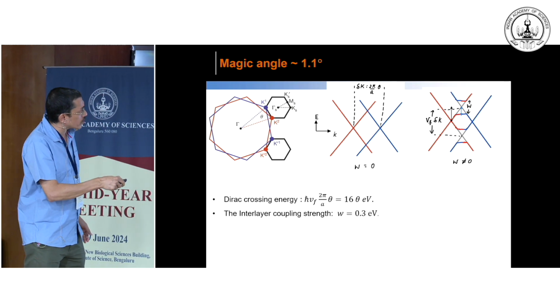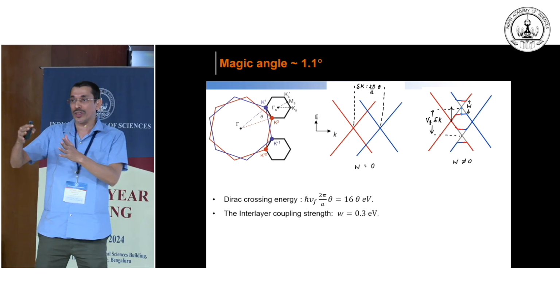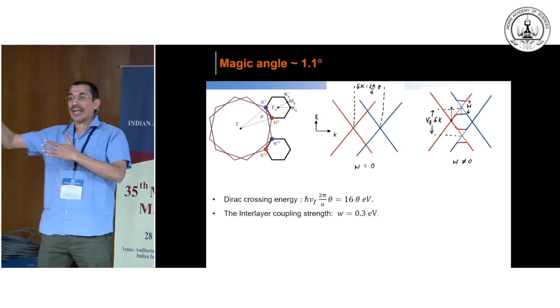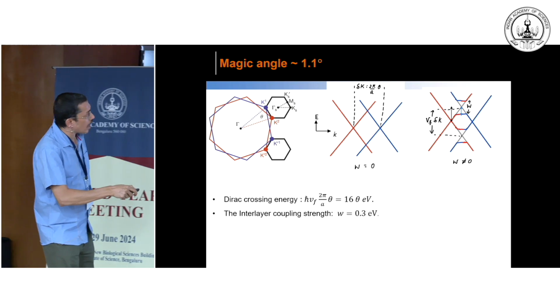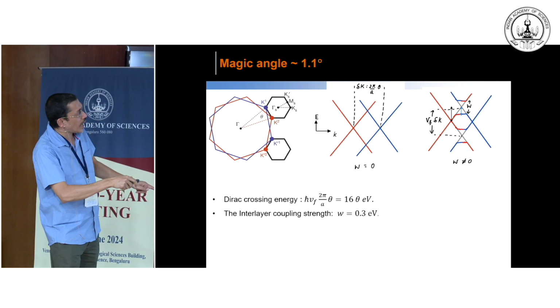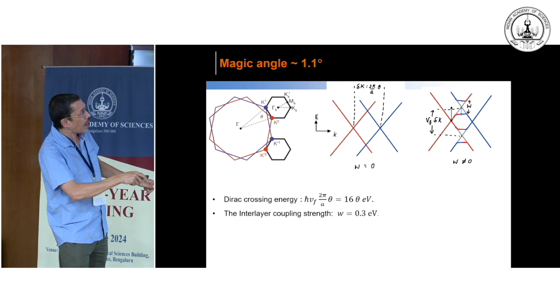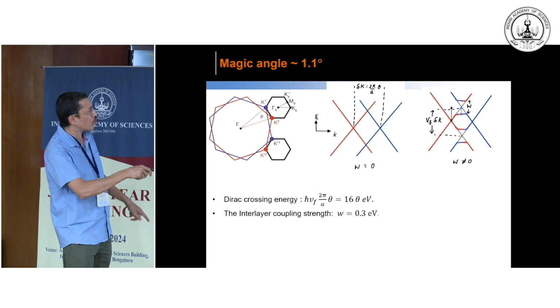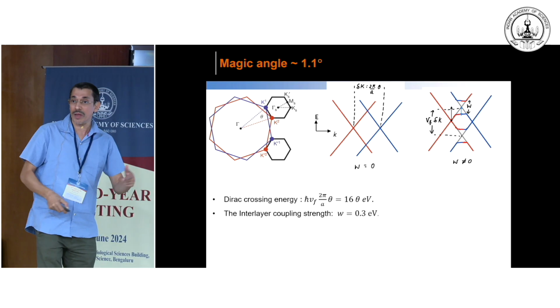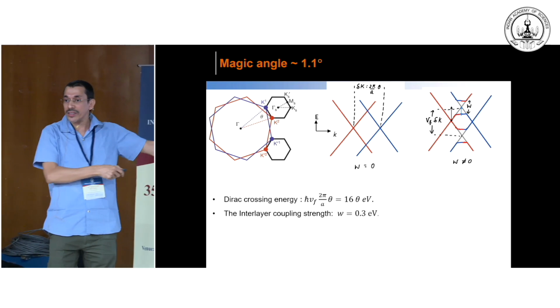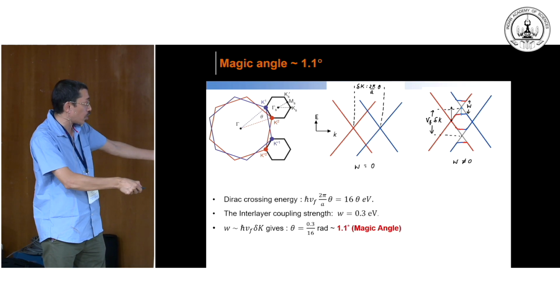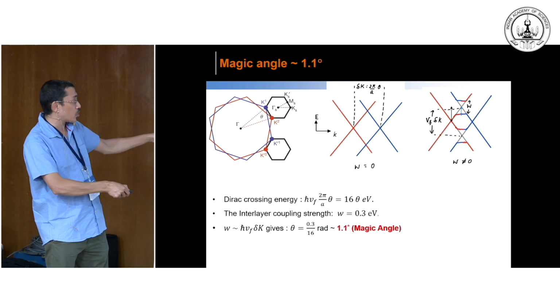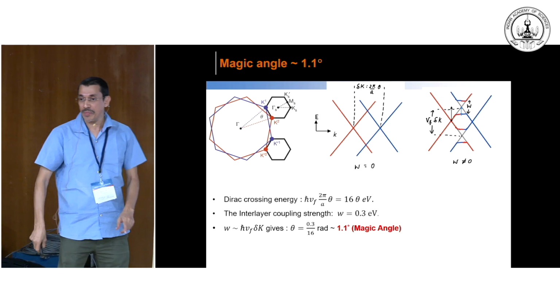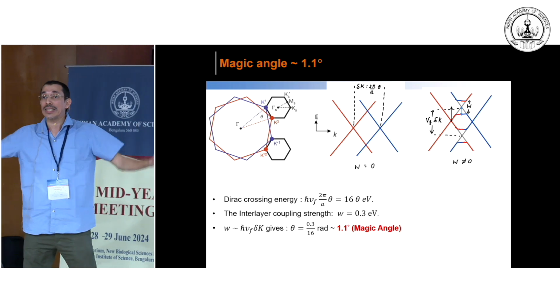So at this crossing point, they will hybridize, and we know that they will create a bonding and anti-bonding orbital. Once they hybridize, they will open a gap, and you can show that this crossing point is required to make a flat band, because we know the hopping strength, which is 0.3 eV, that's the maximum hopping strength. By this argument, you can easily show that I need theta equal to 1.1 degree to have a flat band, without going into any detailed calculation.